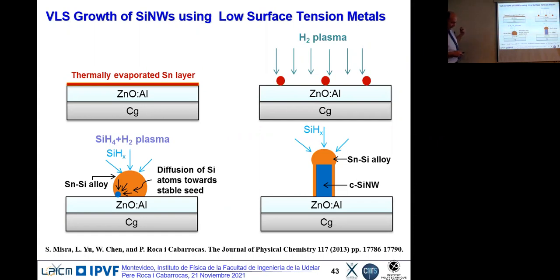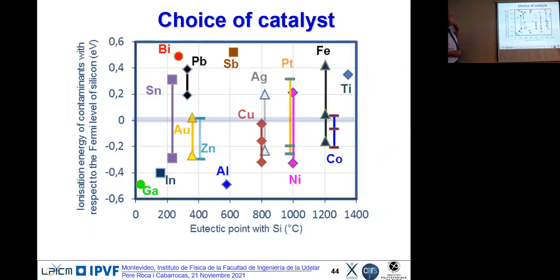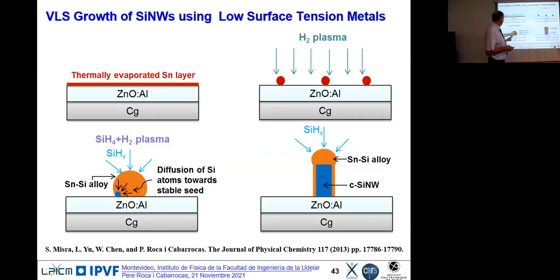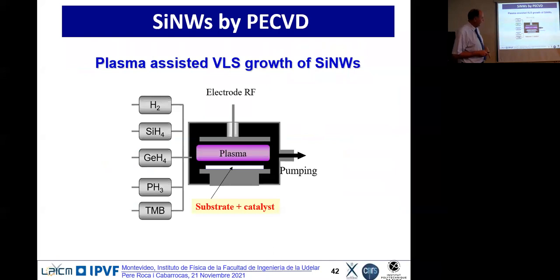And the thing is that when we started this, if you look at VLS growth of nanowires, 90% of the papers are using gold, because gold has a high surface tension and it forms a drop. If you don't have a drop, if this flattens out, you will not grow a wire. You will grow a pizza, a pancake, or whatever, but not a wire. So you have to have a high surface tension.